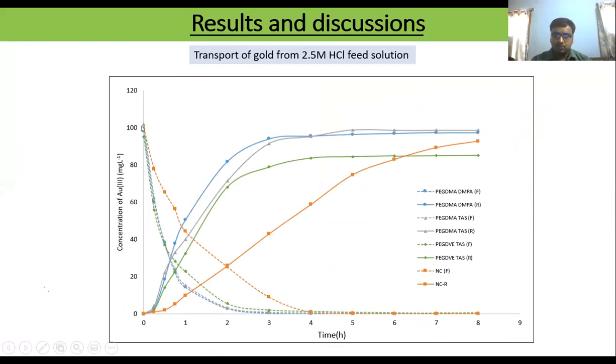So you can see with time, the gold concentration in the feed side is decreasing, and it's completely decreased in 4 hours, in some cases 3 hours. You can see in the cross-linked membrane, it extracted all in 3 hours. But it takes 4 hours for the non-cross-linked membrane. Similarly, when this gold complex is transported through the membrane, you can see the concentration of gold in the receiving side. The transport of gold through the cross-linked membrane is faster. You can see this concentration reaches equilibrium within 3 or 4 hours. But in the case of the non-cross-linked membrane, it took about 8 hours or more to reach equilibrium.